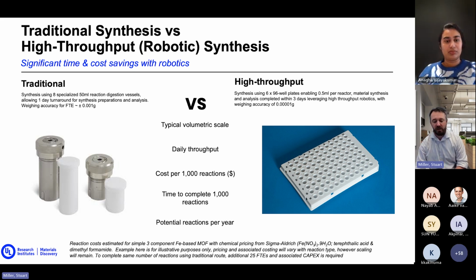It gives you about 2,000 experiments in a year, and it gives you time to be able to cultivate and analyze that data as well. But if you just look at the cost for 1,000 reactions, there's this orders of magnitude difference between the high throughput and the traditional. This is not taking into consideration the outlay of the capex of the high throughput equipment, but it does get you to a point where that capex is rewarded and pays off quite quickly.